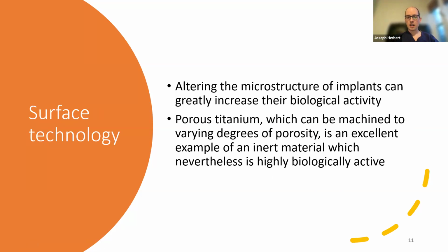So porous titanium is a classic example of this. Titanium, everybody knows we put titanium implants in. Both cranial and spine, they don't change over time. They're very biologically inert. They don't degrade. The body really doesn't react to them. And so it's a very biologically inert compound, which is why we use it. However, if you machine it to have porosity on a nanoscale or microscale, it actually does become highly biologically active.